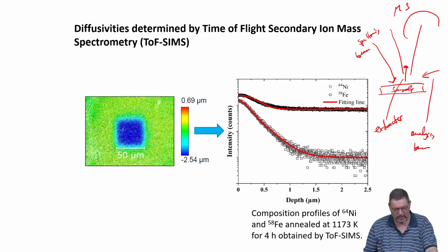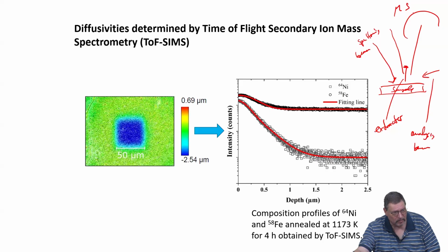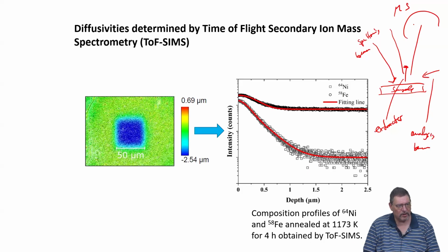That especially is important for digging into the first original surface, because you will always have dirt there. You will have oxides, you will have nitrides, you will have some hydrocarbons which are adsorbed to the surface. You don't want to have this going into the mass spectrometer. And this is why you first clean off the surface, dig a little bit into the material, and only then you start the analysis. But then you only have one detector. This is this mass spectrometer, right, which is then time of flight, and that gives you a direct readout on the flight.